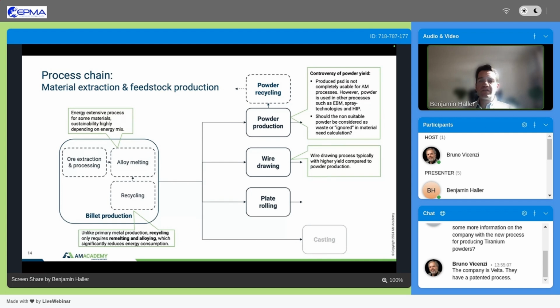So if we consider that the yield is only 40% already during the powder production, there would be a much more significant impact on sustainability. So the question is always, how do we factor this in? Because in reality, of course, we use the non-usable fraction for other processes, either other AM processes like binder jetting that works with a lower PSD fraction, or directed energy deposition, for example, with a higher PSD fraction, or for altogether other processes. But in some cases, especially for aluminum, this is a bit more challenging. So this is already quite important to consider when we talk about sustainability of powder-based technologies. Wire drawing typically has a higher yield and is also less energy intensive, so that's not so much of an issue.